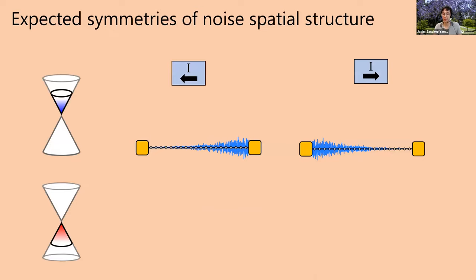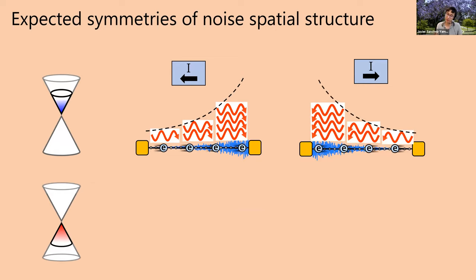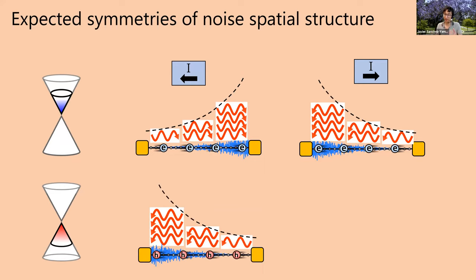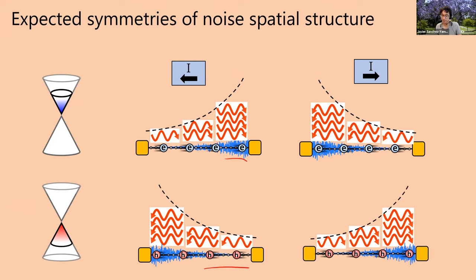So in particular, what we would expect is that a clear symmetry of the noise profile would appear. So what would happen is that as electrons are traveling to the right, the phonons will be exponentially growing to the right, all right? But if you reverse the direction of the current, then it should be growing in the opposite direction. Likewise, if we flip the type of carrier, which flips the sign of the current, if we switch from electrons to holes, which is something that you can do with graphene, then we would expect the direction of this amplification to switch sign as well. So that's how we came up with this idea, then we decided to test it with the NV centers, all right?